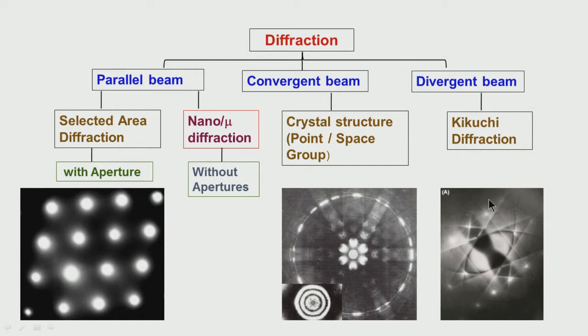And these Kikuchi diffraction patterns are very sensitive to sample orientation. So this could be used to find out whether the beam is exactly at the correct Bragg condition, or how much the deviation is.